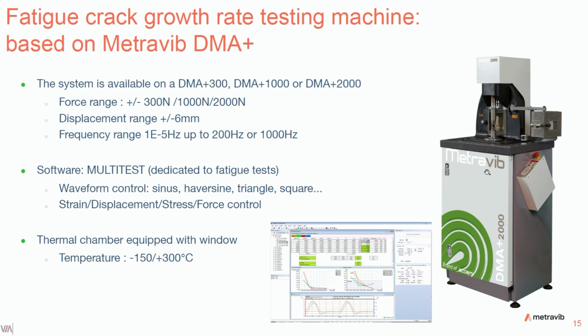And just to give you some technical specifications about the DMA Plus series, we can apply a maximum displacement range of plus or minus 6 millimeters, with a frequency range from very low frequency up to 200 Hz, and 1000 Hz in option. For this system, mainly focused on crack growth, the maximum temperature we can reach in the thermal chamber is 300 degrees. And of course, we can decrease the temperature with liquid nitrogen down to minus 150 degrees.